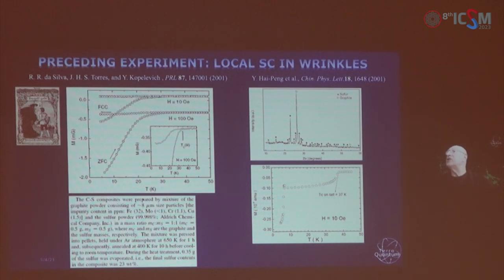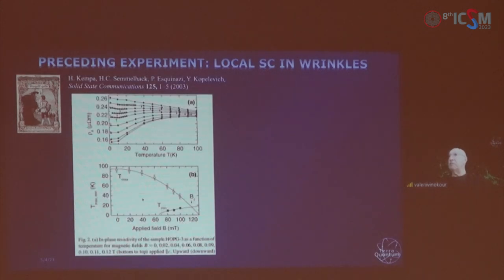The next preceding experiment was also done on graphite-sulfur composite samples, a mixture of graphite powder and sulfur powder, and again you can see the difference between field cooled magnetization data and zero field cooled magnetization data, which show indeed that we do have superconductivity, even at high temperatures.